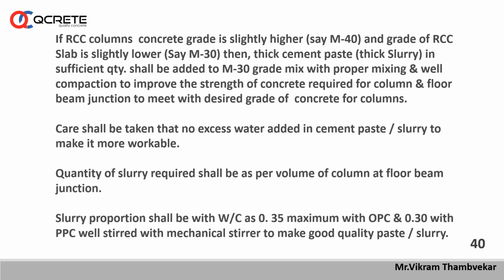Sufficient quantity means if you make a very small quantity of slurry and pour it, it won't help. You have to make a large quantity, say 1 bucket or 2 buckets, depending on the size of your junction. This slurry in sufficient quantity shall be added to the M30 or lower grade concrete which was ordered for your slab, with proper mixing, and of course pouring this slurry as well as the lower grade concrete together. It should be compacted properly to get it mixed with your lower grade concrete, which will improve the strength of concrete required for column and beam junctions to meet the desired grade of concrete for columns. As the cement content increases in that particular part, of course some amount of strength will increase. So these tactics can be followed very carefully.